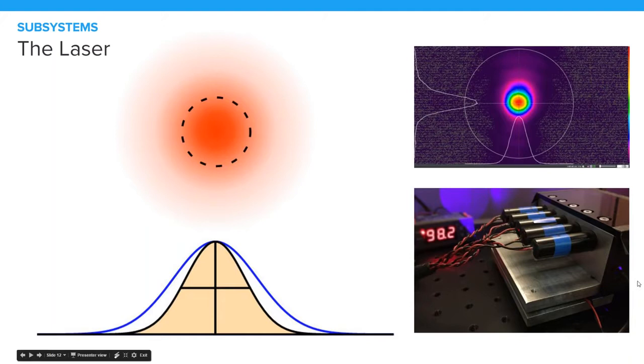On the left, what's with the big gradient curve over there? It's not our exact power and curing profile, but it shows a critical bit of information about our laser, which is namely that despite the laser's diameter being only 140 micrometers across, or 0.14 millimeters, it still cures in a gradient. So the focus of curing is in the center, and then it gradiates out from there. If you take a look at the beam profile in the top right corner, you can see that as well, with the red in the center, and then it goes out to green and then blue and then eventually purple.